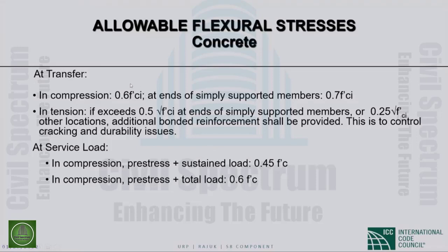And as I mentioned, f'ci is the initial concrete strength. We collect cylinders at the initial stage. Actually, we collect cylinders, it doesn't matter what stage, it has to be during casting. And then we test some of the cylinders initially, depending on when the pre-stress is released. If it's steam curing, we have been doing it at 2 or 3 days. And then we test the rest of the cylinders at service, which would be 28 days typically. At the end of simply supported members, this is the limit, 0.7 f'ci. Now these are in metric, in megapascal. Of course, if I'm using the US system, that would be in ksi, but different factors are applied.